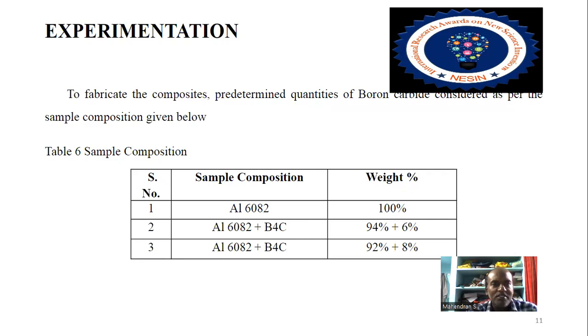There is an experimentation to fabricate the composites. Predetermined quantities of boron carbide are considered as per the sample composition given below. There is aluminum 6082 100 percent. This is the monolithic material. Next one is aluminum 6082 plus boron carbide: 94 percent of aluminum 6082 and 6 percent of boron carbide. Next one is 92 percent of aluminum 6082 and 8 percent of boron carbide.